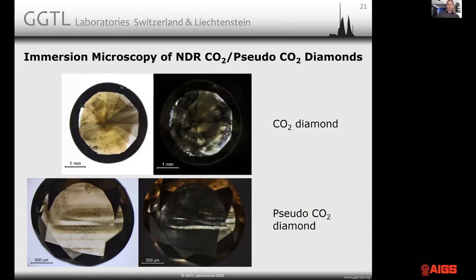If you put it in the cross polarizers, you can see that some extinction shows up that's very likely inclusion related in these stones. You can see there are colorless areas and there are brown areas. The brown areas are the ones that are rich in CO2. The colorless areas are actually CO2 free.